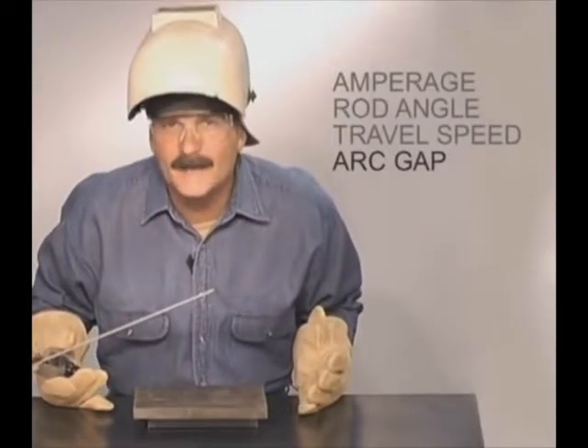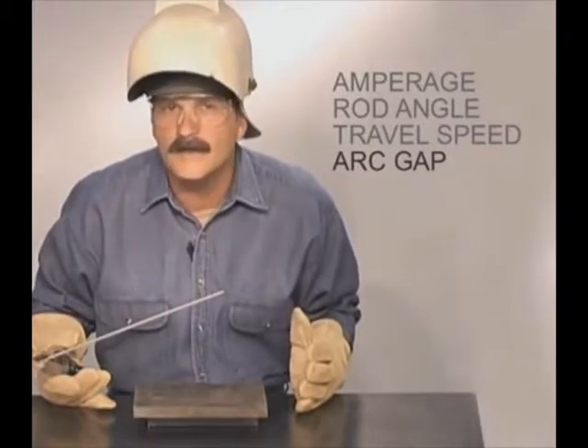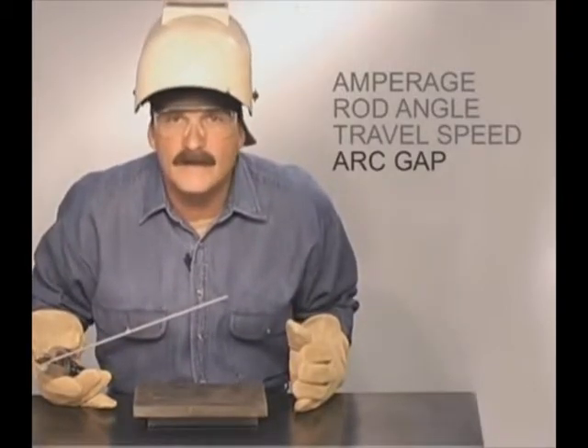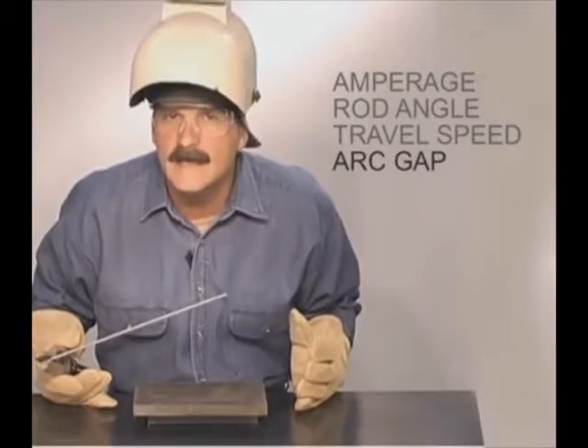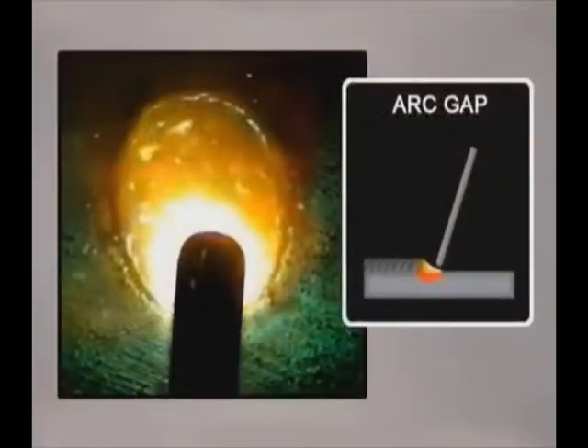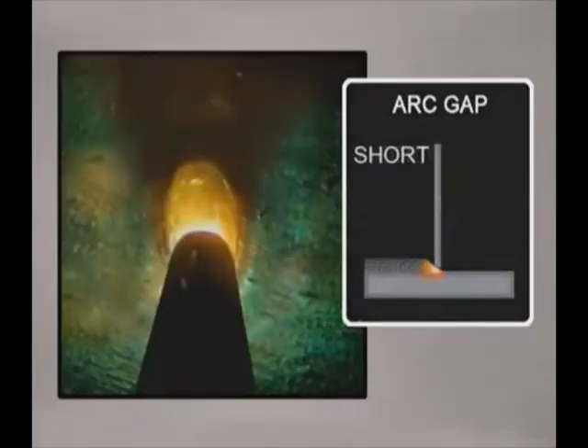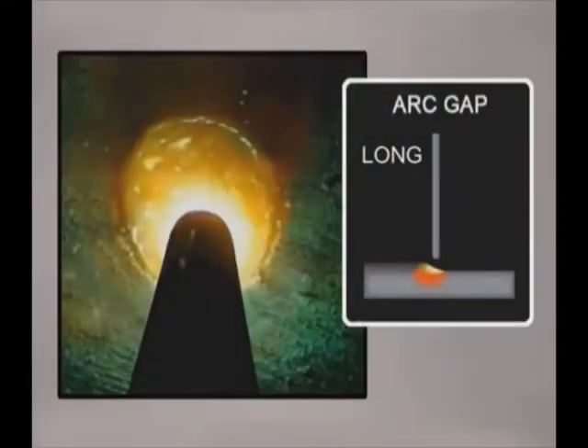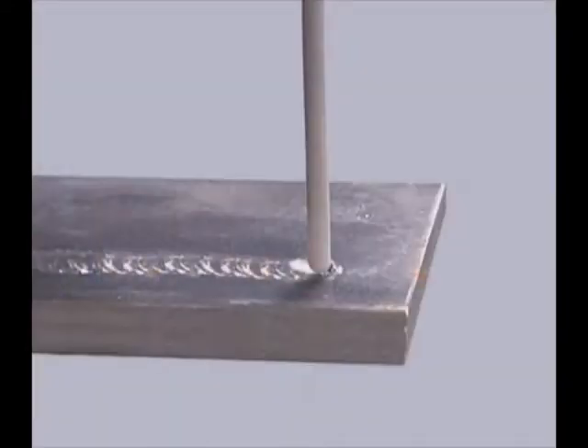You want to avoid jamming the rod right down against the metal or long arcing too far, but you can use slight variations in the arc gap to help control the heat and shape the weld. This is difficult to measure, but a medium arc length is used to build up weld. Shortening the arc reduces the heat, cooling down the weld puddle. Try using a shorter arc gap on vertical up with 7018 when you want to build up more weld. Slightly lengthening the arc causes the heat to increase, spreading the puddle out, and is used with a more perpendicular rod angle for making smaller beads or flattening the weld on heavier metal.